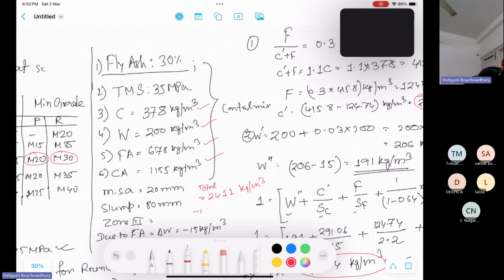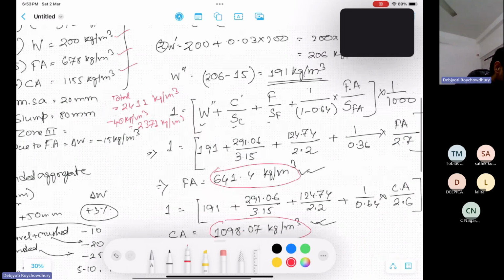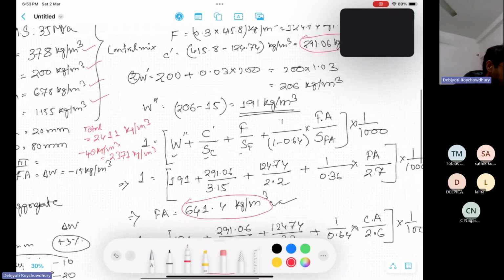Reduction in weight density is by how much? 40 kg per meter cube. It is coming like 49, so it is around 2371 kg per meter cube. And you can both check it with this if it is coming closer or not.